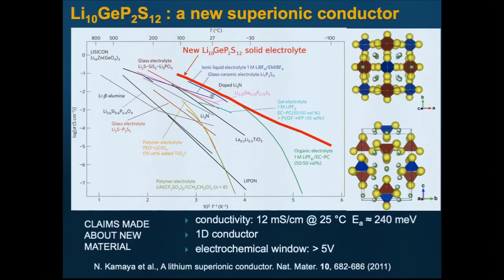Well, in 2011, there was an interesting paper in Nature Materials by Kamaya et al. who showed a new conductor, lithium germanium thiophosphate, LGPS as it's called now, which on an Arrhenius plot has the same conductivity at room temperature as liquid electrolytes. Interestingly, it has a lower activation energy than liquid electrolytes, meaning at low temperatures it's even better than the liquid electrolytes. They claimed very high conductivity, 12 millisiemens per centimeter, which is exactly where organic solvents sit. They claimed it was a one-dimensional conductor, with a super high electrochemical stability window of over 5 volts.